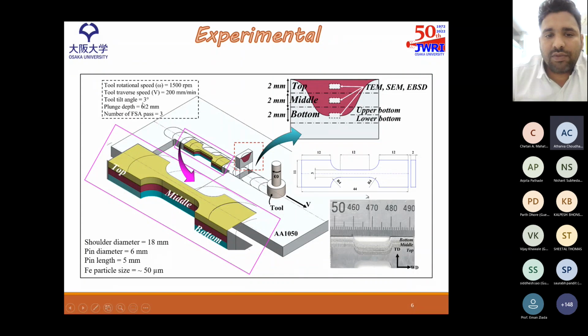And the parameters which we have used are 1500 RPM tool rotational speed and 200 millimeter per minute. And we have carried out the number of passes, that is 3, with 100% overlap. And you can see the sample which is formed here. And we have sliced the tensile specimen sample into 3 parts, 3 layers, which can be shown here.